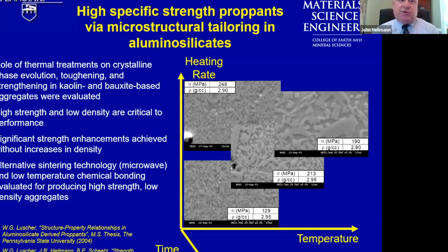So lower sintering temperatures and shorter sintering times, which could be achievable by higher heating rates, are good things to consider, provided the mechanical, thermal, and physical properties of the resulting proppant is not modified. So we were able to demonstrate in the case of bauxite and kaolin ores that we could sinter the materials at substantially lower temperatures by manipulating heating rates, going to higher heating rates, and achieving fine grain size microstructures, appropriate crystalline phase assemblages, and specific gravities to yield high compressive strengths. This was good news at the time. Industrial processes were able to be modified, economic benefits and environmental benefits were achieved.